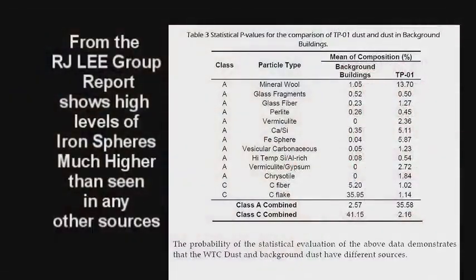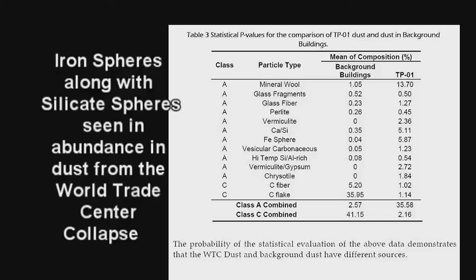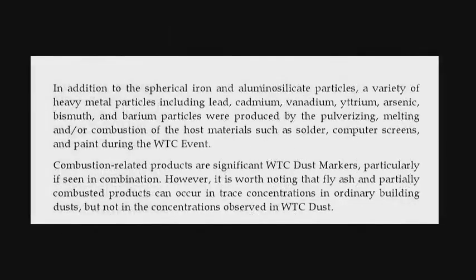From the R.J. Lee Group report, high levels of iron microspheres, much higher than seen in any other source. Iron spheres, along with silicate spheres, seen in abundance in the dust from the World Trade Center collapse. In addition to the spherical iron and aluminosilicate particles, a variety of heavy metal particles including lead, cadmium, vanadium, yttrium, arsenic, bismuth, and barium particles were produced by the pulverizing, melting and or combustion of the host materials such as solder, computer screens, and paint during the WTC event.